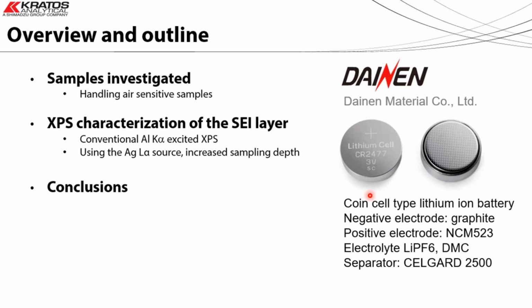And initially I thought the SEI layer was a bad thing, but it in fact isn't. It's absolutely vital in the performance of the lithium ion battery. And it really dictates the performance in the reversibility of charging and discharging. So it must be lithium ion conducting to allow lithium ions to transport towards the anode, but importantly electronically insulating, so that you're not getting continuous reduction of the electrolyte. And the presence and stability of the SEI, as I've said, is fundamental.